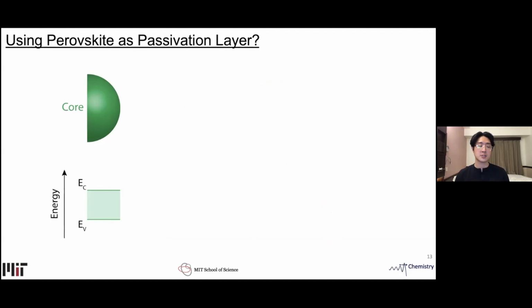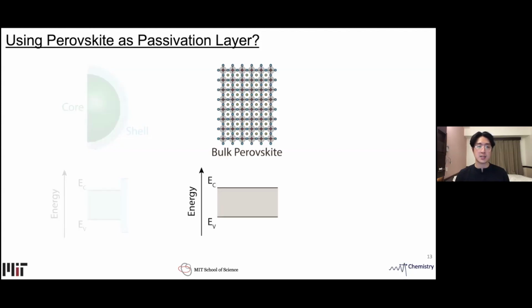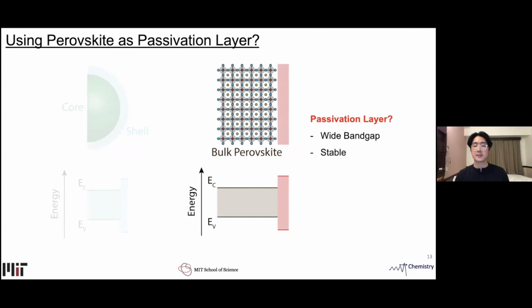A strategy that has worked really well in colloidal semiconductors, such as quantum dots, is to overcoat the core with a shell material that has a wider band gap. Can we translate the same idea to a bulk perovskite, where we add a thin passivating layer? This passivating layer has to have a wide band gap, needs to be chemically stable, and also has to be defect tolerant.